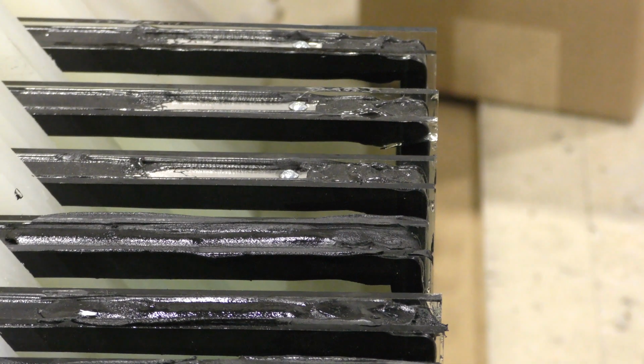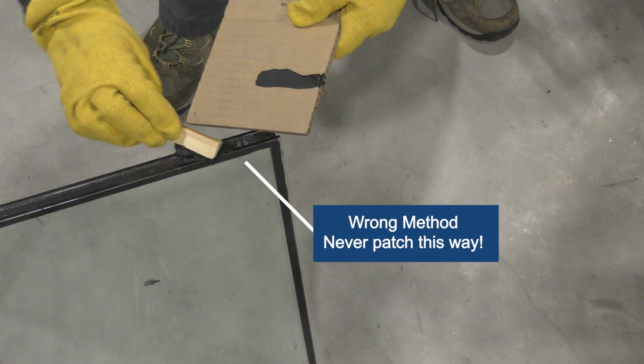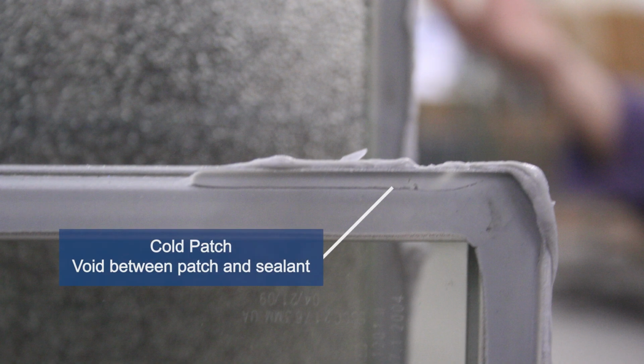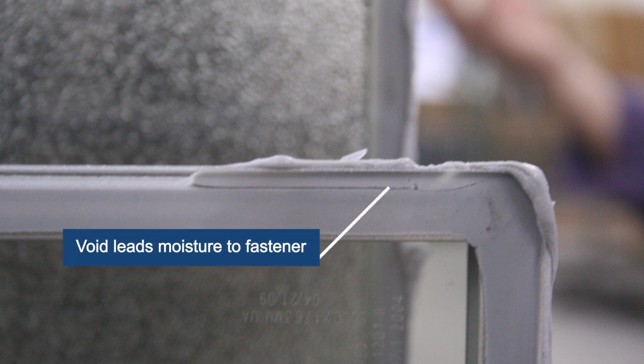Use a silicone pad to smooth the hot applied patch sealant material to the vent hole area. Do not use a stick, spacer, or glove to smear the material into the vent hole area. These items will quickly conduct heat away from the sealant and result in the sealant not being hot enough to weld to the existing sealant.